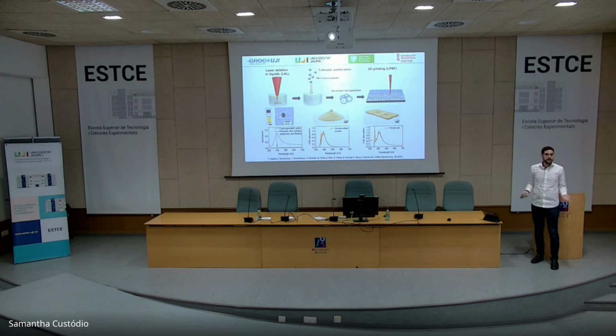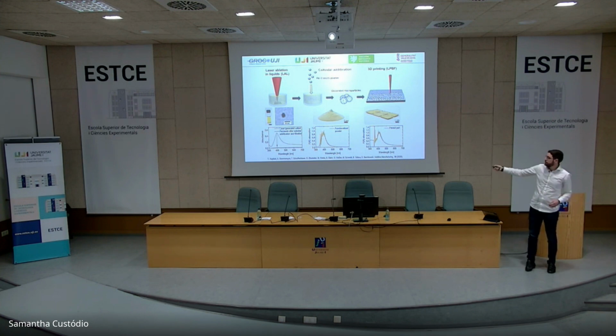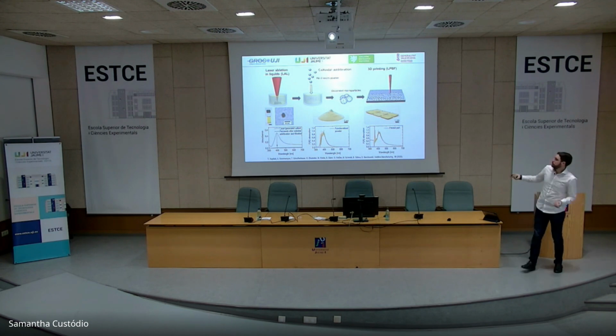So we start our process in our lab with our laser. We irradiate some gold silver target immersed just in water. We generate nanoparticles in the liquid. You see here the colloidal nanoparticles around 10 nanometer size, and they have this plasmonic absorbance at around 400 nanometers, more or less. Then we add the PA12 micropowder, the nylon microparticles, and we control the pH, and then the nanoparticles go to the surface of this powder.